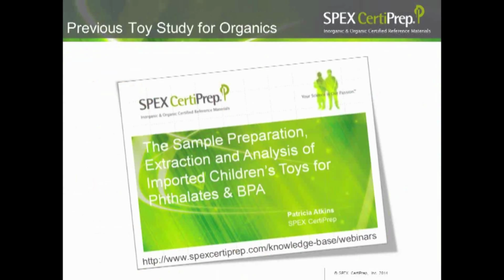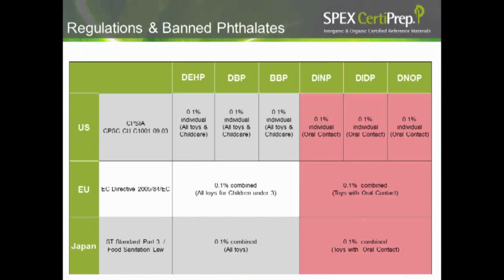If you're interested in some of our previous work on the organics, like phthalates and bisphenol A in toys, you're more than welcome to look at our webinar, the sample preparation, extraction and analysis of imported children's toys for phthalates and bisphenol A. I'm going to give you a little snapshot because this shows you why we decided to pick these PVC toys. During that experiment, we were basically following the regulations from around the world for the US, the EU and Japan when it came to 6 banned or restricted phthalates, the DEHP through the DNOP. In the US, we're allowed up to 0.1% of each of these phthalates, but especially ones with oral contact, things in the pink, those are the ones that have 0.1% for each of those. In the EU and Japan, you're up to 0.1% combined for the different groupings of phthalates.